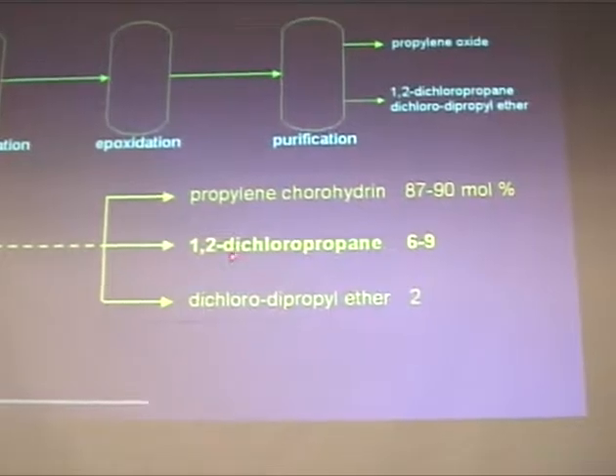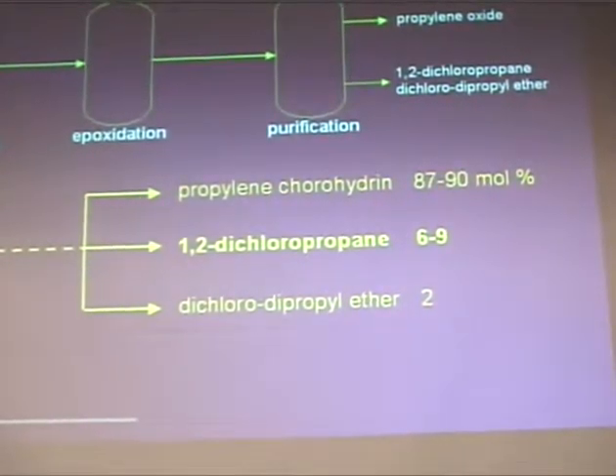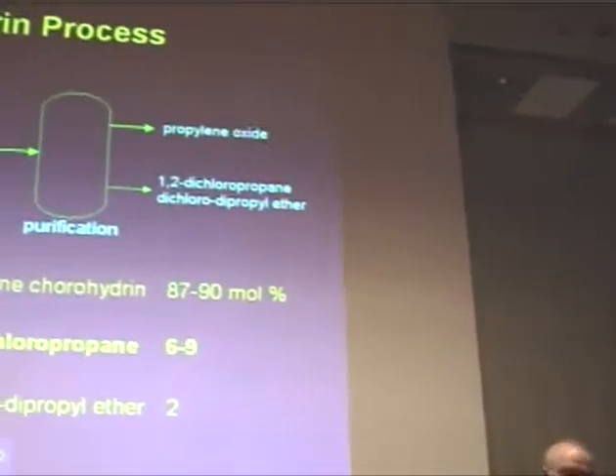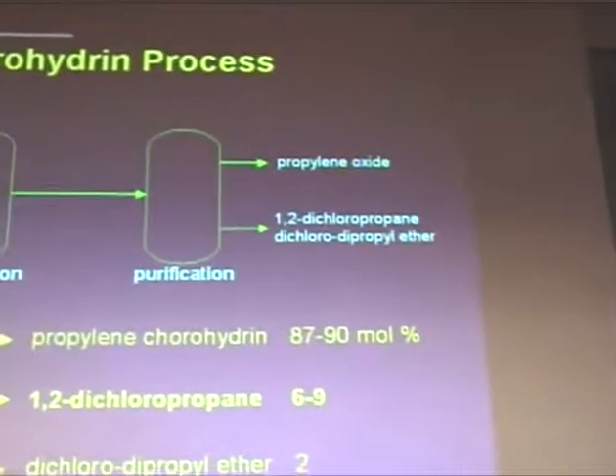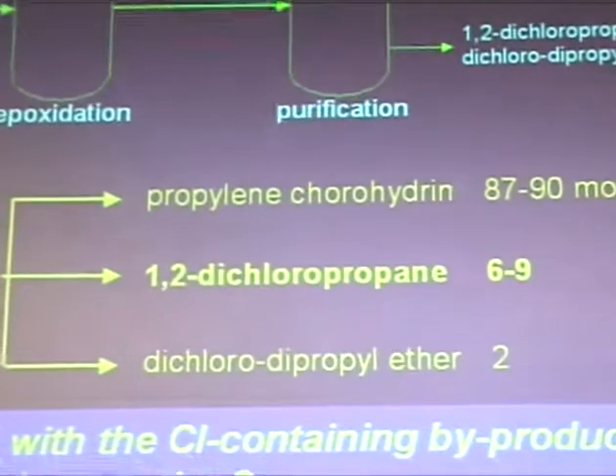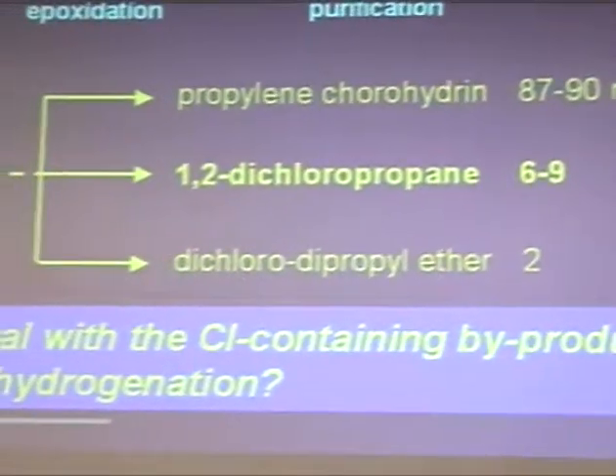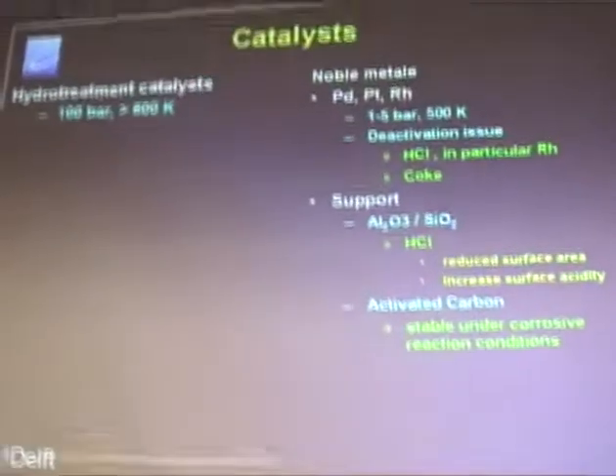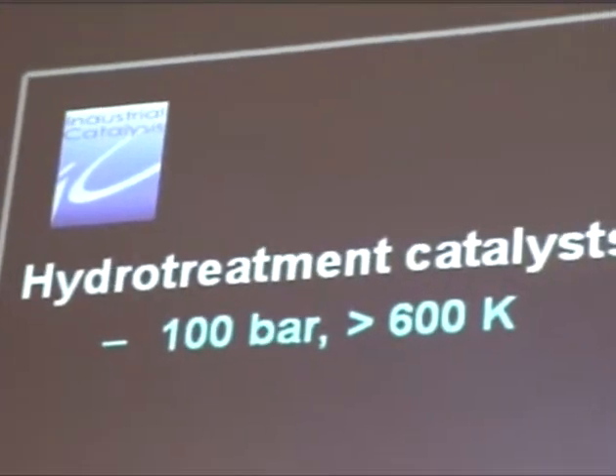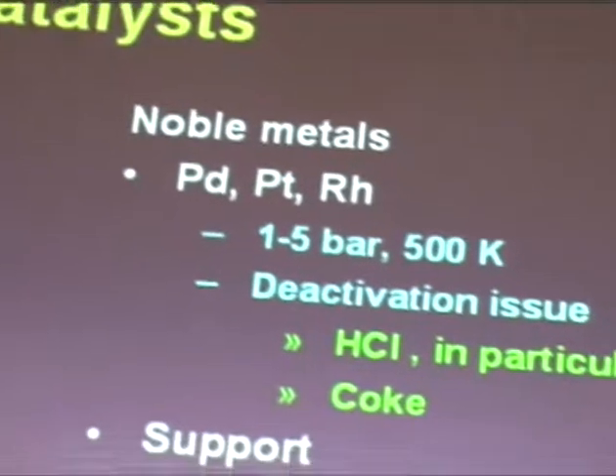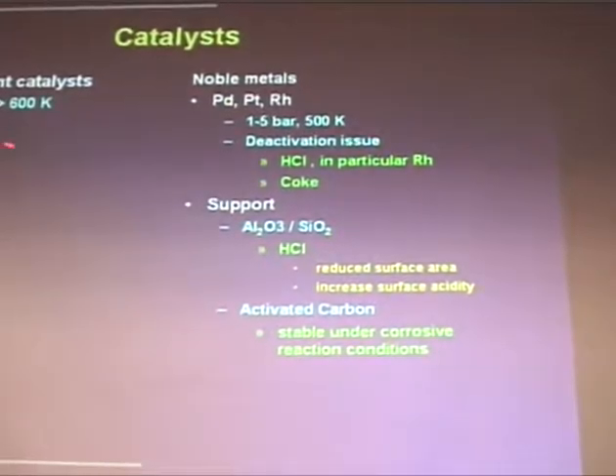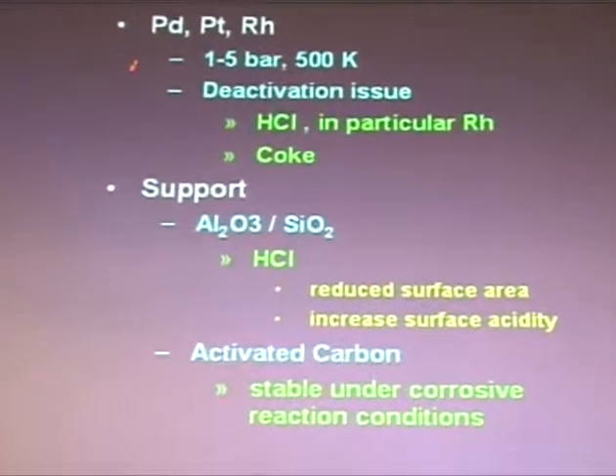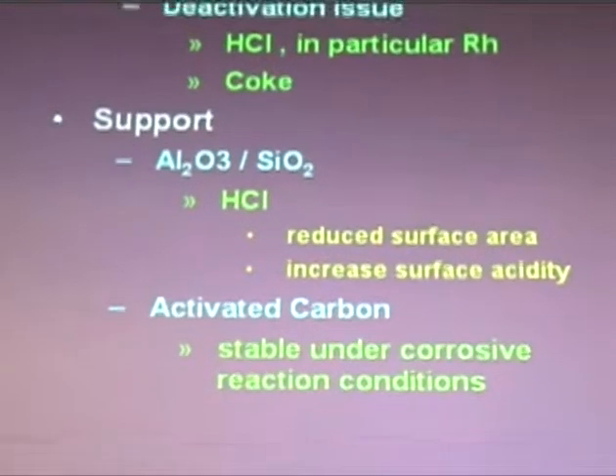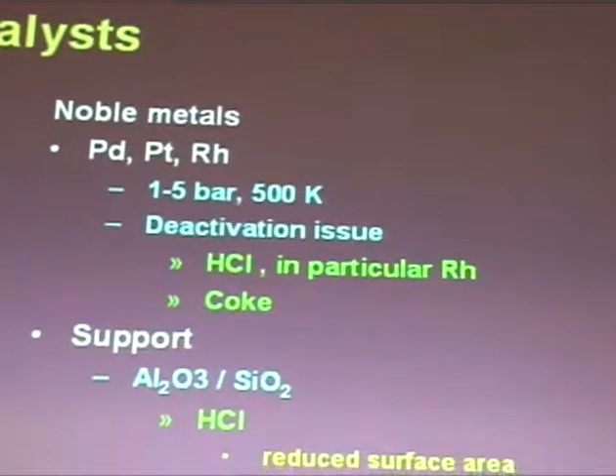And dichloropropane is 6 to 9%. That's quite a high number, of course. And then the question is how to deal with it, and could you use selective hydrogenation to transform that molecule. And when you look at that, there are a few options, and there's some literature, not so much. You can use hydrotreatment catalysts at a rather high pressure and temperature. And also you could go to noble metals, and they are much more active. Say atmospheric, 500 K. But as people in this audience will be aware of, deactivation is the major issue, of course. You should expect it. HCl is a point, rhodium is out, coke.